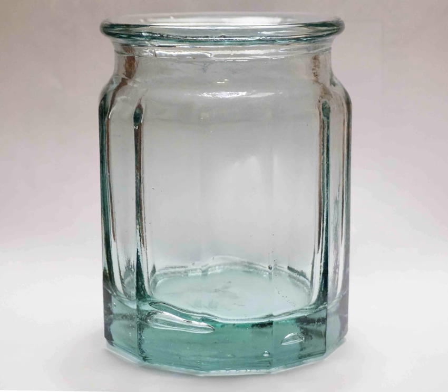One is sodium carbonate, soda, which lowers the glass transition temperature. The soda makes the glass water soluble, which is usually undesirable, so lime, CaO, calcium oxide, generally obtained from limestone, some magnesium oxide, MgO, and aluminium oxide, are added to provide for a better chemical durability. The resulting glass contains about 70 to 74% silica by weight and is called a soda-lime glass. Soda-lime glasses account for about 90% of manufactured glass. Most common glass contains other ingredients to change its properties.